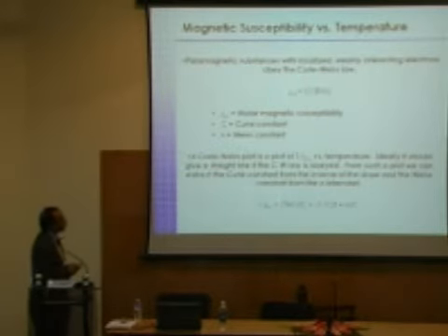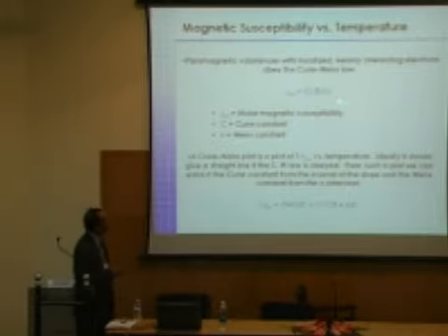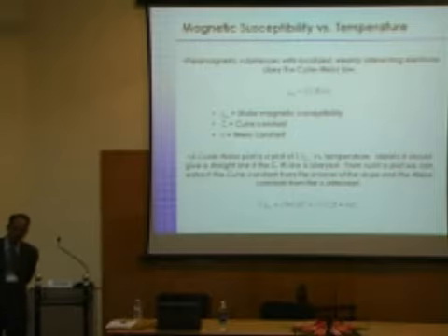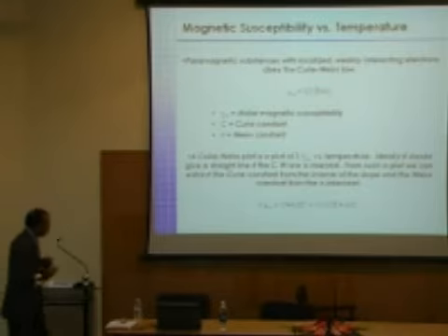So by measuring the magnetic susceptibility as a function of temperature, which I will show you in the plots in the next few graphs, one can estimate the Curie constant, which will tell us how many unpaired electrons an atom has. That is how you can retroactively find out whether my oxidation state of the metal is 3+ or 2+ or 1+, because transition metals, as you all know very well, can exist in multiple valence states, and this is one way of figuring this out.